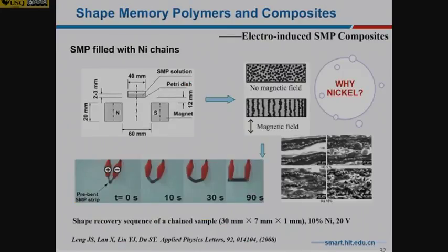So this is, we start with the nickel. So why are we using nickel? Because nickel is a material sensitive to both the magnetic field and the electric field. So this graph shows you that with no magnetic field, nickel will distribute homogeneously in the polymer. If you apply a magnetic field, nickel can form a chain. So the idea is, during the curing, during the fabrication, we use a magnetic field to form a chain. Then after curing, the chain still survived. You can see from the SEM that after a few cycles of bending, the nickel chain still survived.